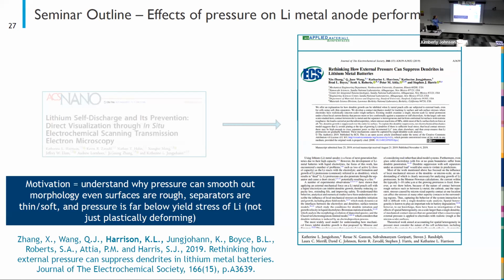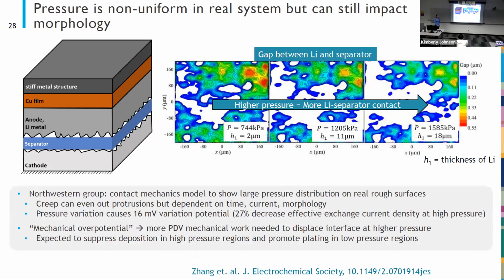So we started collaborating with this group at Northwestern that did a lot of the work for this paper, and they were experts in mechanics modeling, and we thought it would be very interesting to look at this problem that way. So this is a schematic of the type of system that we're looking at. We're simulating rough surfaces on the anode and the cathode. We have a separator in the system, and they used a contact mechanics type of model to understand if you apply a certain amount of pressure and the lithium is growing, how is that pressure going to be distributed when you have these rough surfaces, and how much of a variance is there going to be in the pressure?